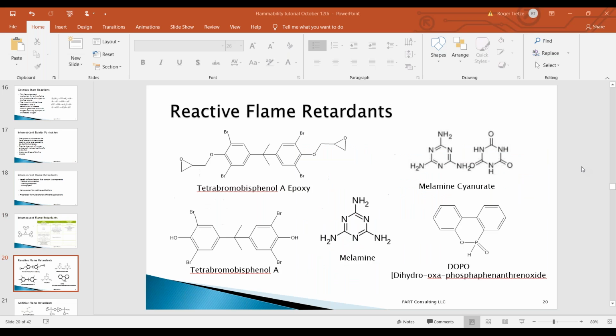So the next slide. Here we have basically reactive flame retardants, and these are very well known reactive flame retardants. In the electronics industry, you have both the tetrabrom bisphenol A on the lower left and tetrabrom bisphenol A epoxy right above it. They're very common in many applications. They've been commercially available for many, many years. In the center, you see melamine, and on the upper right is the melamine cyanurate. They are, in effect, also curing agents. So they're very effective to work into the backbone of the polymer, particularly epoxies.